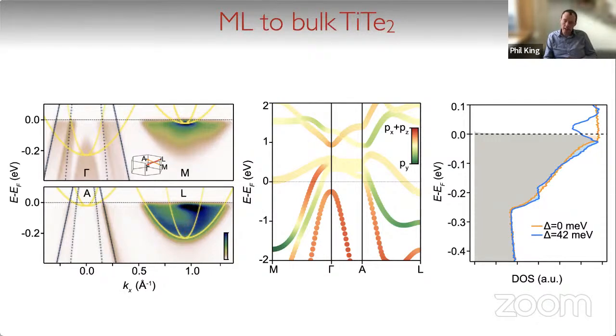But if you look at this as a function of KZ, you can see that these states are really moving in and out. The spectral weight's really going in and out. And so I think the remnant spectral weight there is just an experimental reality. Basically the extremes correspond to the high symmetry points where the dispersion is lower, and that's why when you integrate over KZ. Exactly, yeah. Okay. Exactly. So I think in these spectra, you're normally seeing your spectra dominated by the turning points of the dispersion. Okay.